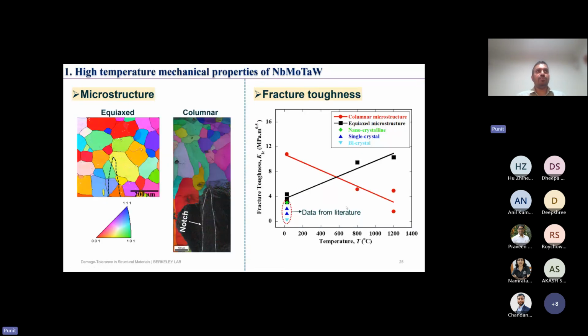So we had these microstructures which are equiaxed as well as columnar grains ahead of the crack tip. So we went ahead and we evaluated the fracture toughness of this material with different microstructures at different temperatures. So we found these interesting fracture toughness values in this material. At room temperature, you can see this is the data from literature. The equiaxed microstructure shows a fracture toughness of about 4 megapascal root meter, and columnar microstructure shows actually much higher fracture toughness at room temperature. But as you increase the temperature, you see the fracture toughness of columnar microstructure goes down, and equiaxed microstructure shows higher fracture toughness as the temperature is increased.